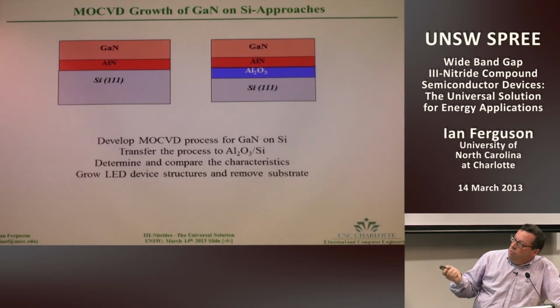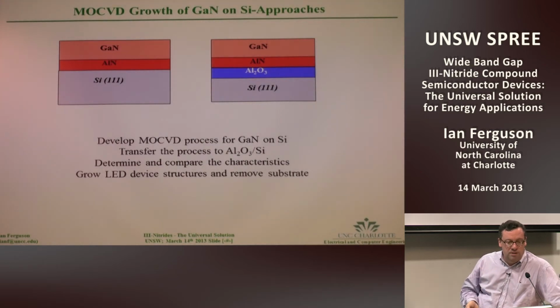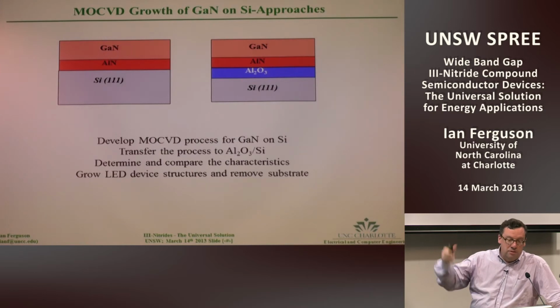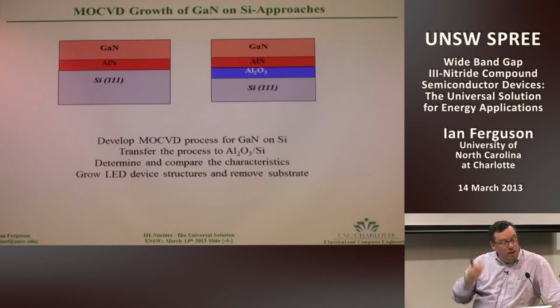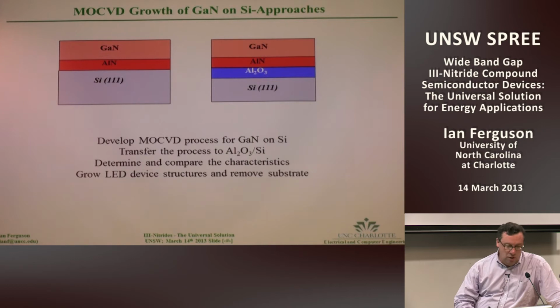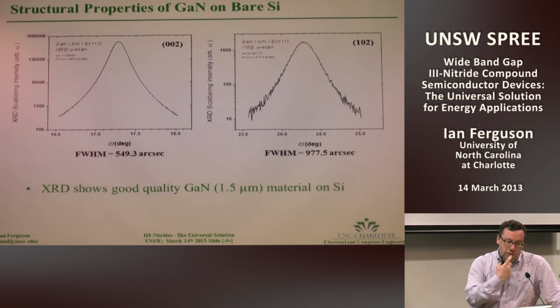So we compared the growth on both the silicon and then with these different types of aluminum oxide buffer layers. Most of the technology for growing the nitrides has been on sapphire, which is aluminum oxide. So what we were doing here was putting in an aluminum oxide buffer layer.